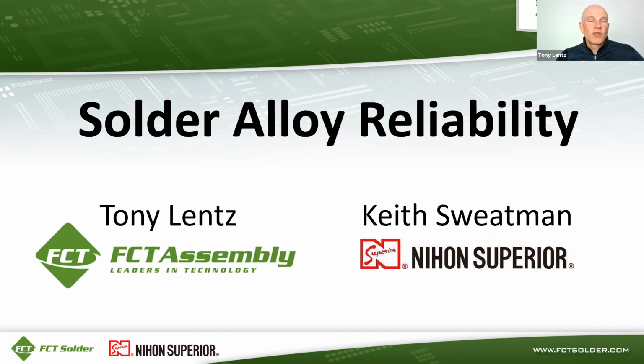Whereas if you add, say, 4% bismuth to the solder, that extra amount that won't stay dissolved will precipitate out as individual bismuth particles. And that's where they become particle strengtheners. Or when you add silver to any kind of a tin copper mixture, you get Ag3Sn particles. And those are not soluble in the tin, so they precipitate out as fine particles, like I showed in the